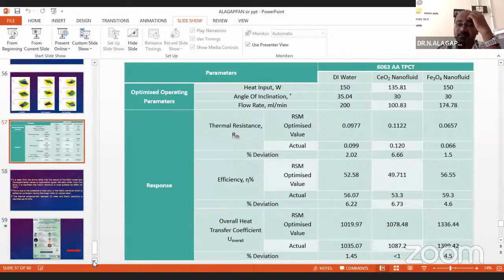The actual reading is also taken and the deviation is very minimal: 2.02, 6.66 and 1.5. Similarly, efficiency is 52% while using DI water, 49% while using CeO2 nanofluid, and 56% with Fe3O4 nanofluid. And the overall heat transfer coefficient is also higher when we are using Fe3O4 nanofluid in 6063 AATPCT. Next slide, sir.